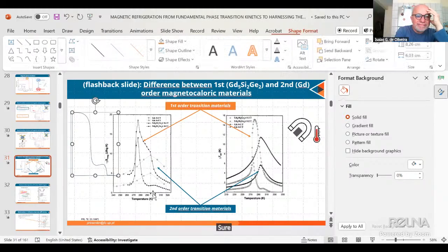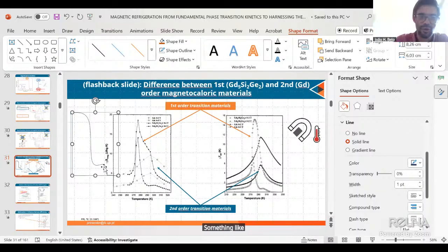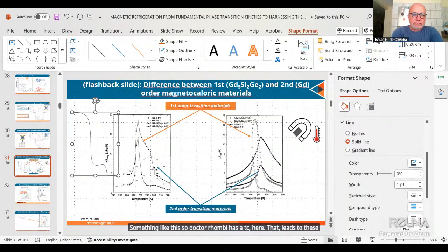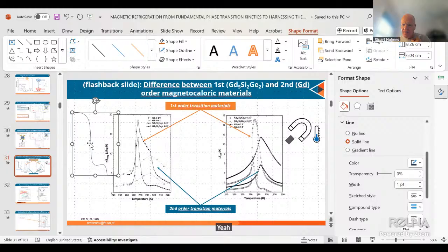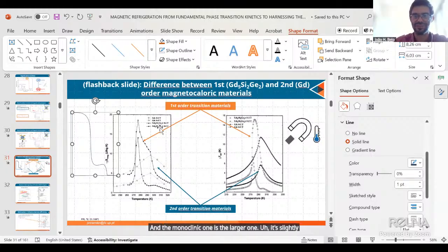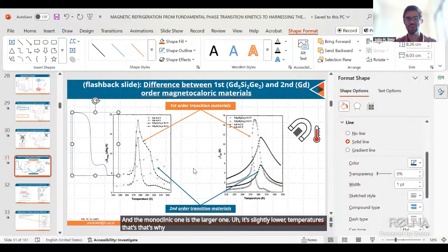Something like this. So the orthorhombic has a TC here that leads to this delta S at higher temperatures. And the monoclinic one is the larger one at slightly lower temperatures. That's why this structure on the peak. Thank you. That's very, very nice explanation.